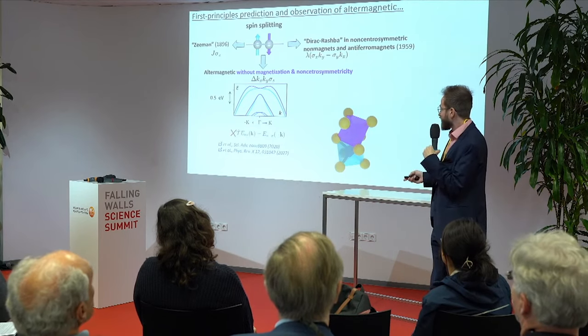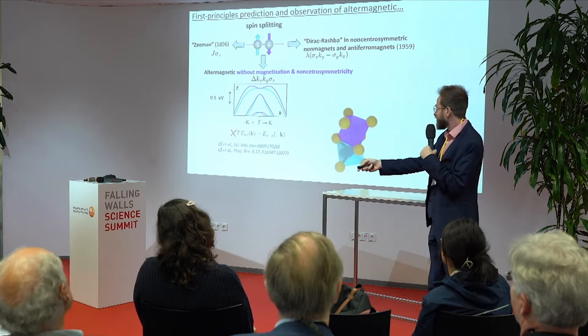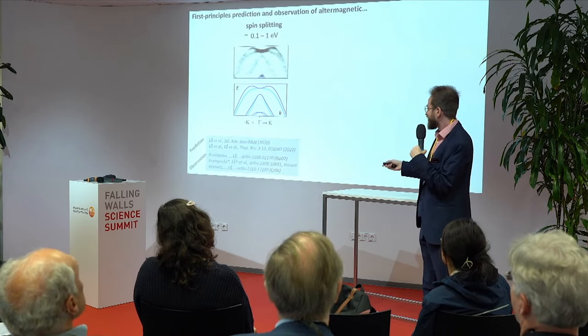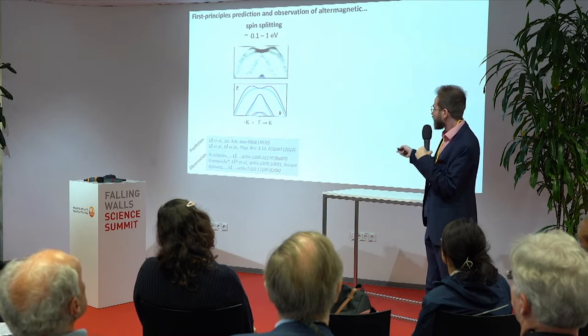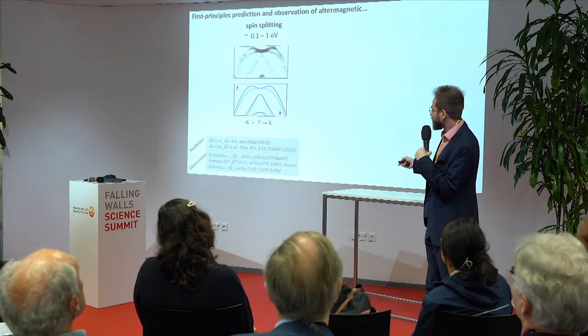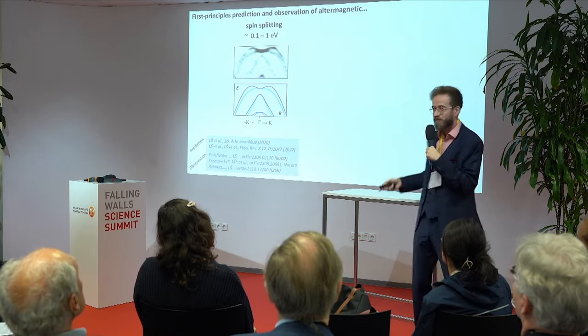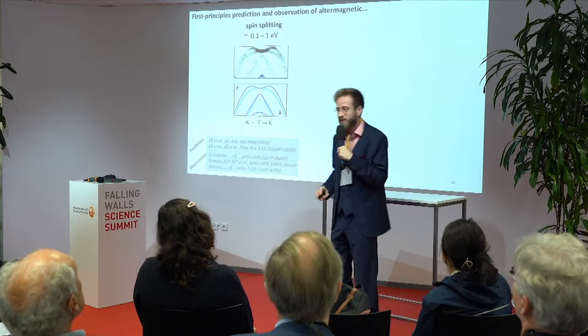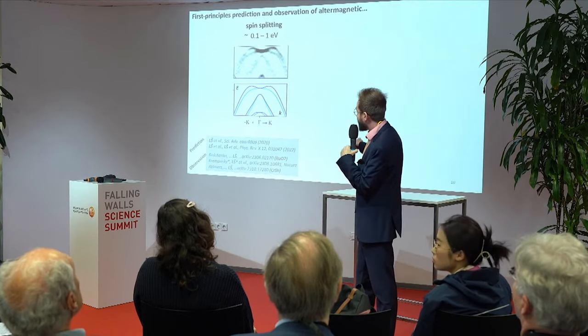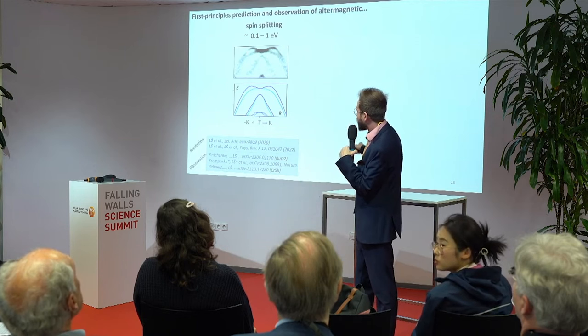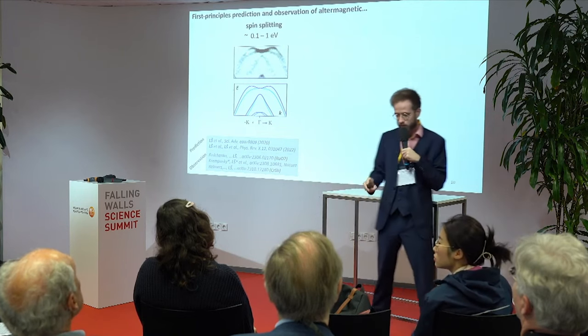So we were actually even able to measure the splitting experimentally, in collaboration with our colleagues from Switzerland, and you see that the prediction and the experiment correspond beautifully. And you see that there is indeed a huge scale, which corresponds to hundreds of millielectron volts.